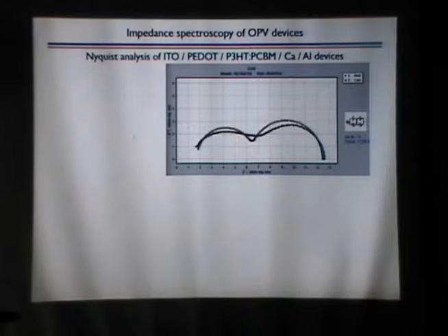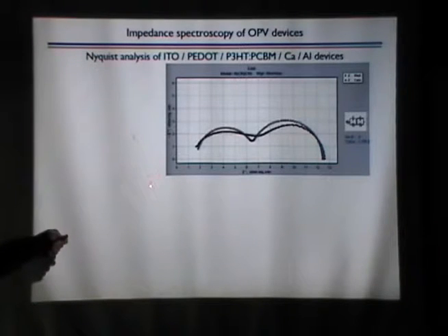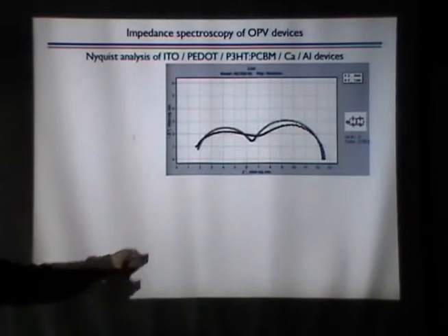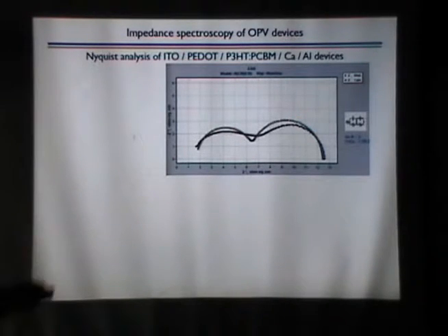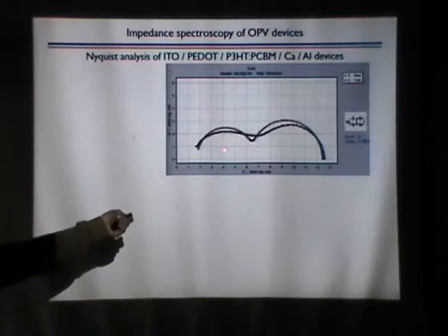Okay, so a little sidetrack into impedance analysis for the specialists in the audience. How do we actually extract those carrier densities from impedance? We can take our device, and the first thing we want to do is fit an equivalent circuit to the device using a capacitive model. For that, we'll make a Nyquist plot. That is, plot the negative imaginary component of the impedance against the positive real component of impedance. In this case, the red curve is what we measure, right? We take the device, here's the device structure, just measure the impedance and then plot out the imaginary versus real part. And the green is a fit to an equivalent circuit.